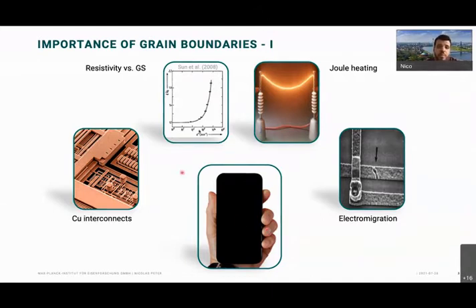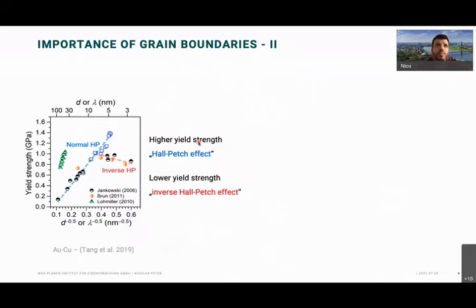Decreasing the grain size actually also means increasing the fraction of grain boundaries inside your material. So there must be something going on. Another example, more on the mechanical side, is the well-known Hall-Petch effect that says if you decrease the grain size, the strength of your material goes up. And then there's also something called the inverse Hall-Petch effect. If the grain size is getting very, very small, some people argue that this effect reverses and you decrease the strength of the material. So clearly, again, grain boundaries might play a significant role in this effect, because if only the grain size changes, also only the fraction of grain boundaries changes.